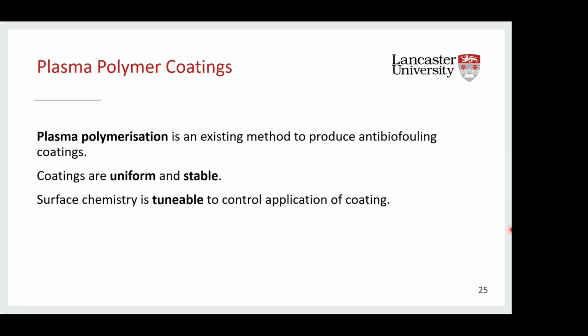This activated monomer can then partake in various fragmentation and rearrangement reactions, which initiates polymerization. By simply placing a substrate in the reactor during that process, the fragments are going to naturally combine at that surface, forming a cross-link structure, which is then your plasma polymer coating. These coatings are both uniform and stable, and in doing this process we actually have the ability to produce ultra-thin film coatings. So for example, I work with samples that are between 1 and 100 nanometers in thickness.